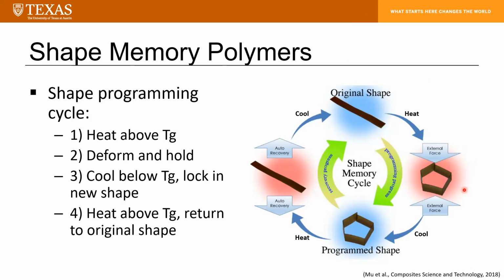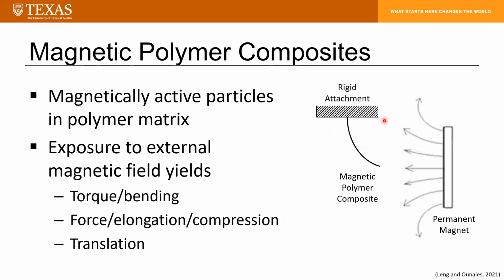Afterwards, you cool the part, and this locks in the strain energy. So you've got this semi-permanent shape down here. And if you want to return to your as manufactured shape, you simply heat your part once again above the glass transition temperature, and this allows the polymer chains to release that stored strain energy, and the part will unfurl back to your original shape.